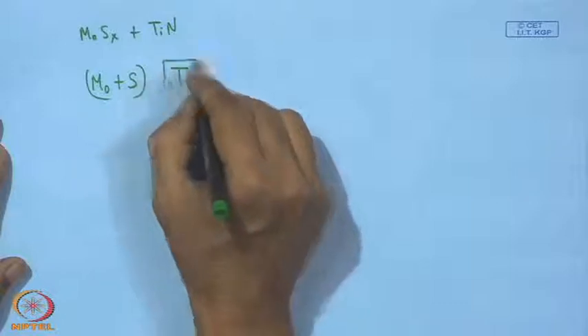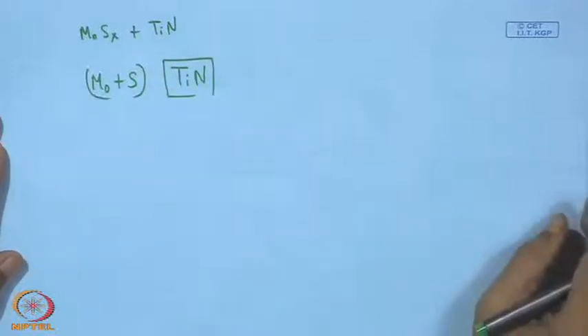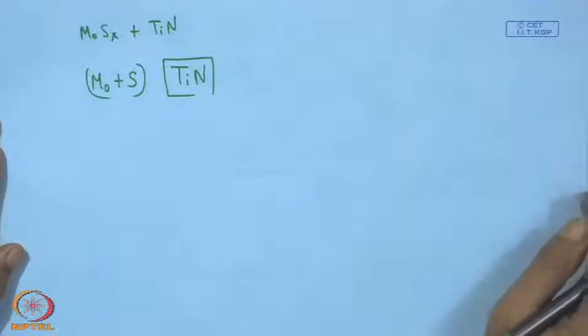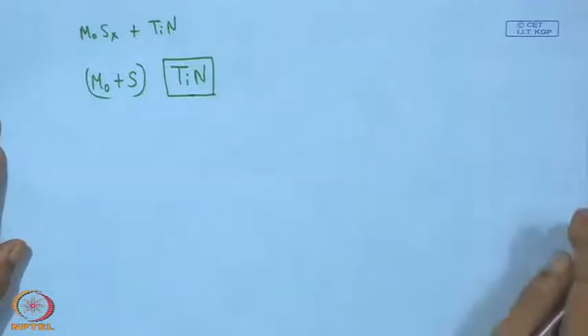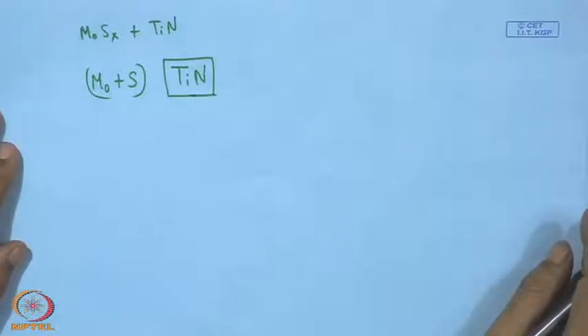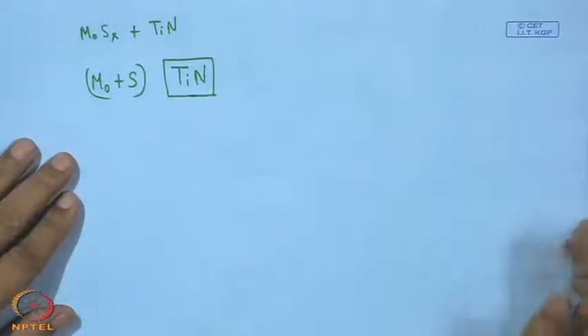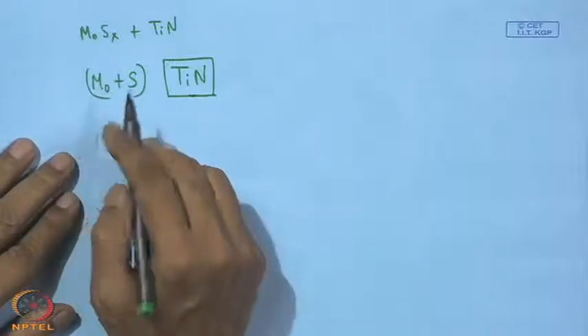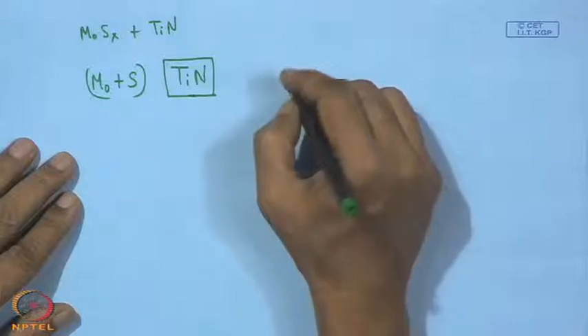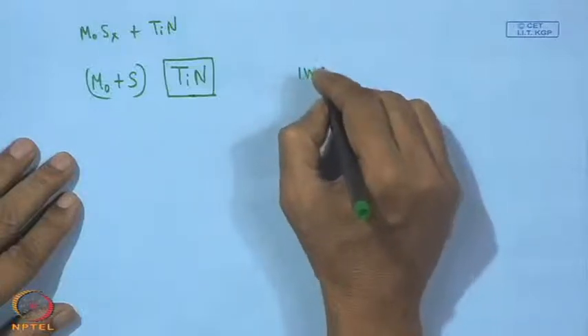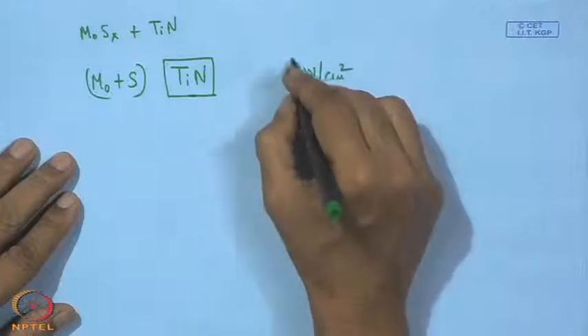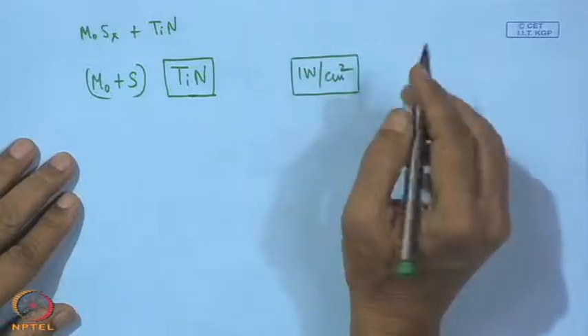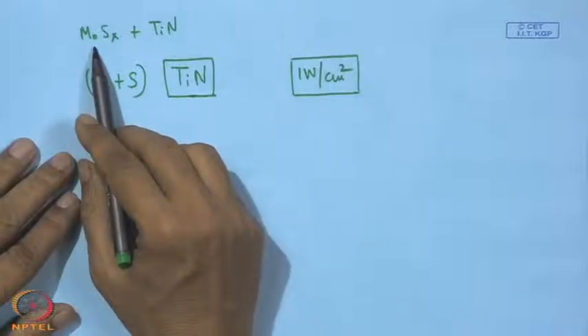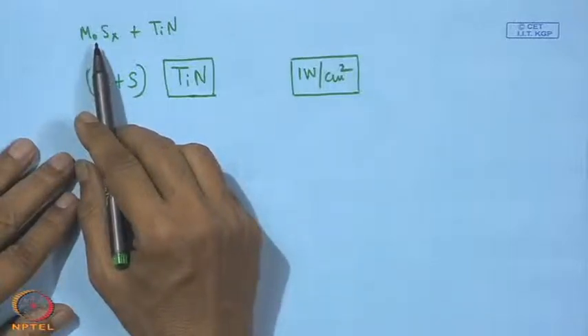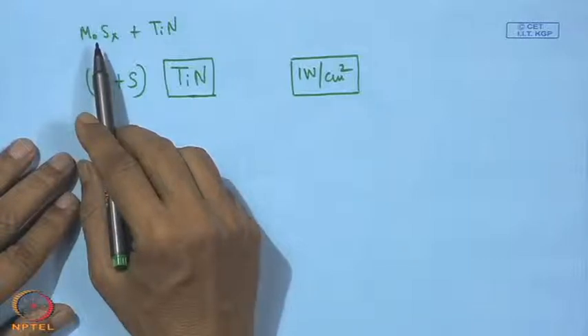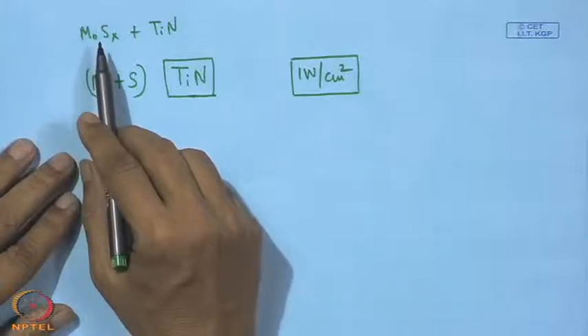So, TiN is on one side and this Mo plus S. This is something quite important and interesting to know, and for that, what can be done in this case? There is an operational restriction with the cathode power of the MoS2 target, say about 1 watt per centimeter square, and with this it may not be that easy to vary the cathode current for the MoS2 target. That means the molybdenum disulfide cathode current cannot be that conveniently varied.